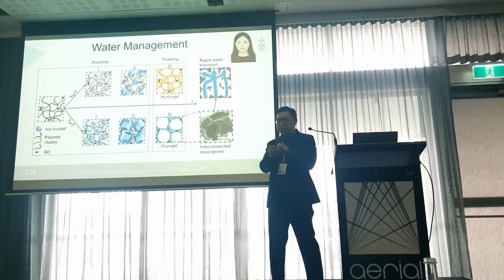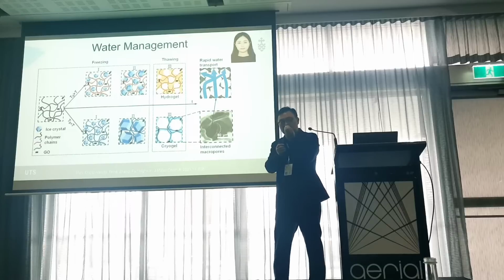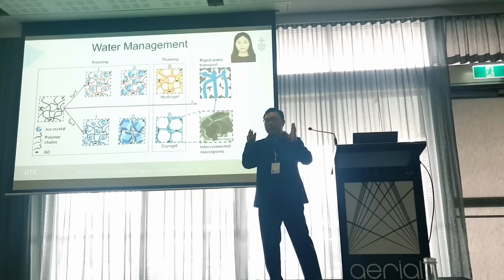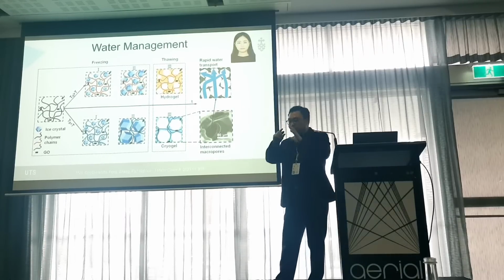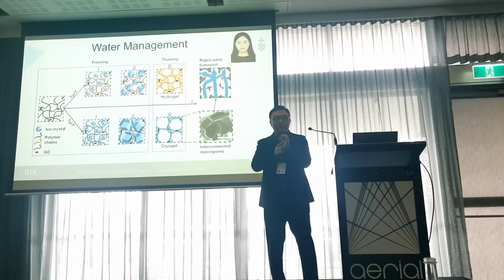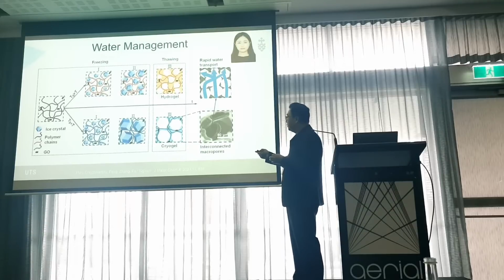So therefore, in the hydrogels, the growth of the water crystal was limited. So finally, we obtained a micropore structure with a lot of small pores. Yeah, that's the case of PVA hydrogels.